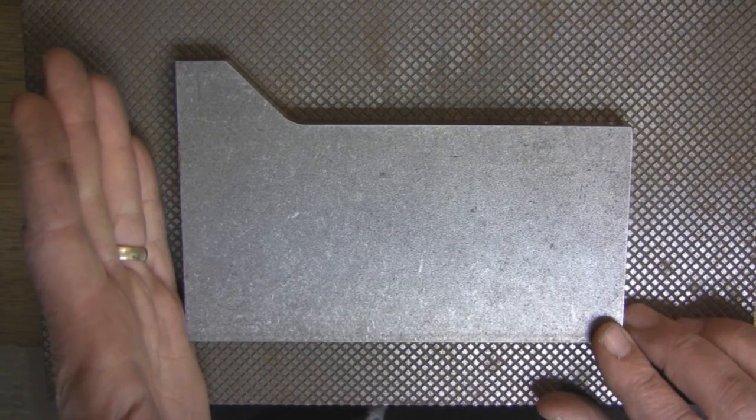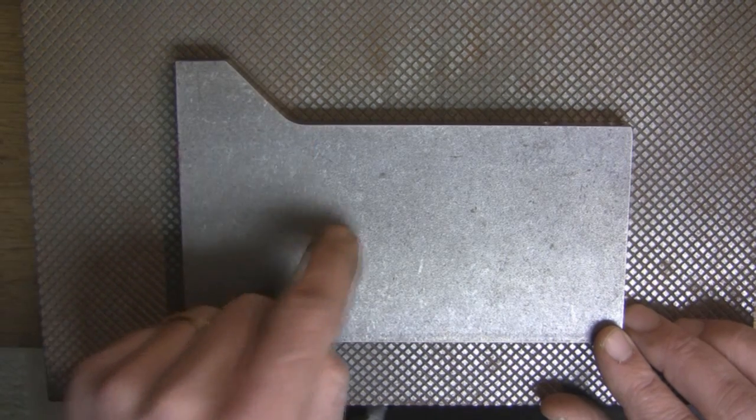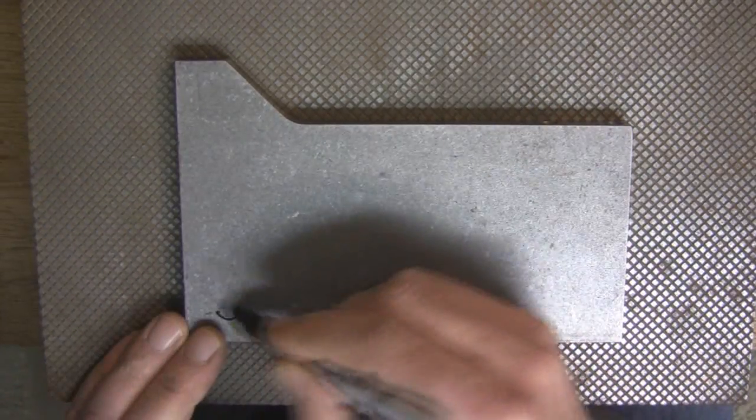Then I took this cutout, cut this out five thousandths out of square, even with a half inch radius in here. So the thing about cold roll that I forgot, it's got a skin on it, because of the way it's cold rolled, and it's very sensitive to being cut open. You can drill holes in this all day long, and the holes will be fine.